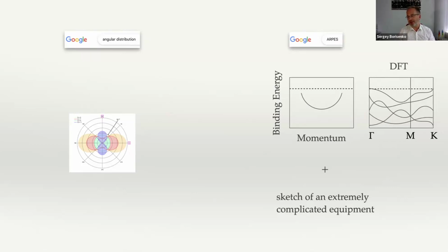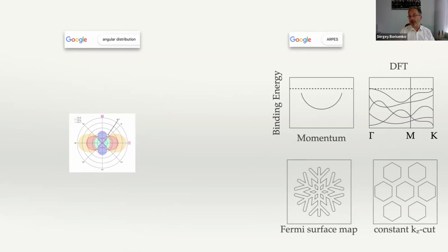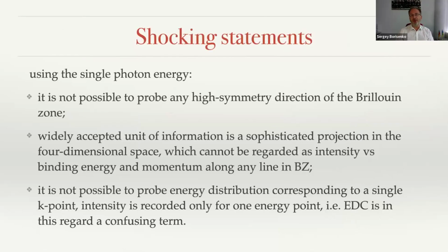Another thing is that nearly every ARPES paper, and I showed you a couple of slides back, the same situation, the ARPES data, this Cartesian plot, is directly compared to the DFT result with the band structure, with high symmetry points, sometimes even overlapped, and in many cases they do agree very nicely. Another very often compared data set is the Fermi surface map, which is compared to the constant kz cut. One cuts the Fermi surface at a particular momentum and compares with ARPES data, and this is usually taken for granted. So ARPES is a good method to measure intensity distribution as a function of binding energy and three-dimensional momentum. I show you a couple of shocking statements, which were also interesting for myself.